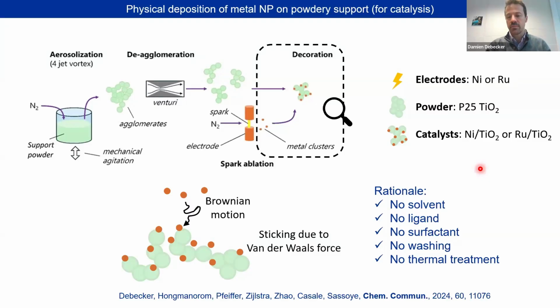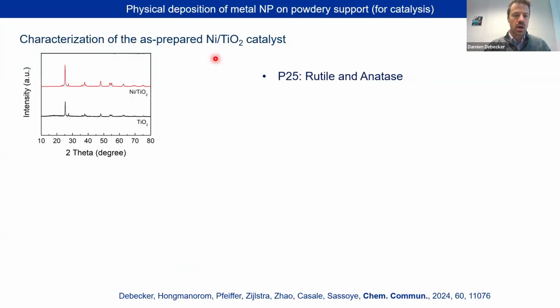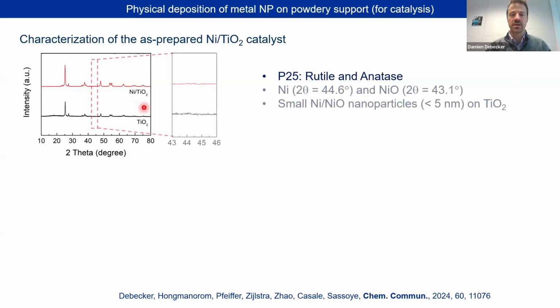So I think it's quite an elegant way to prepare this kind of metal-supported catalyst. If we analyze those catalysts, of course, if you analyze by XRD the pristine TiO2 support, you get anatase and rutile phases as expected. If you analyze the supported catalyst, you see almost the same thing.